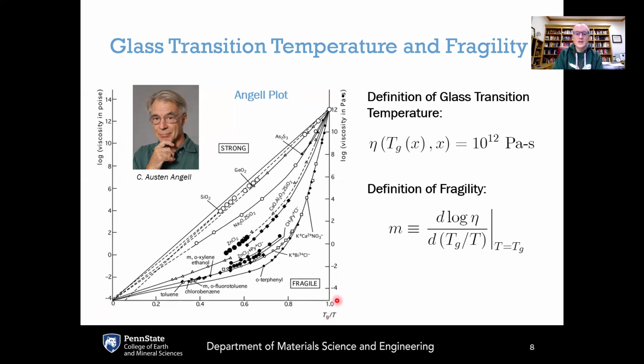So 1 on this x-axis here corresponds to the glass transition temperature for each one of those different glass forming systems. And Angell defined the glass transition temperature to be the temperature at which the viscosity of the supercooled liquid is equal to 10^12 Pascal seconds.